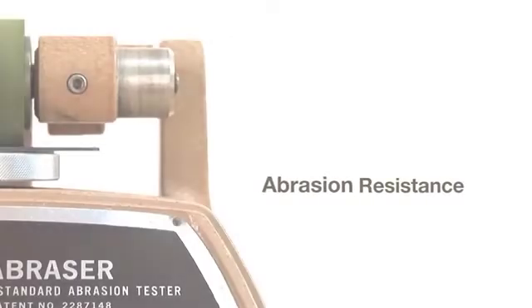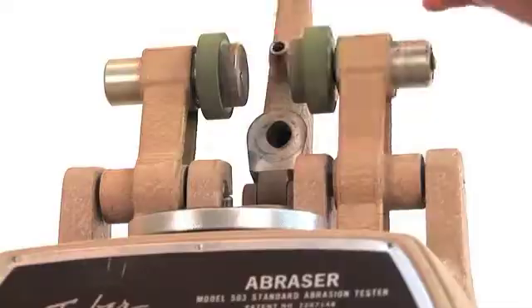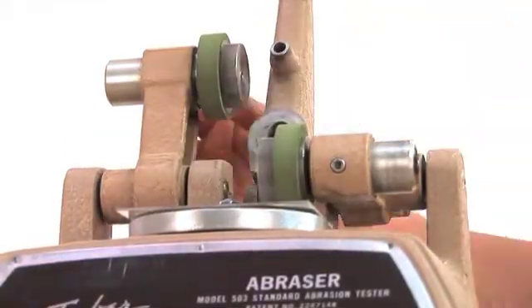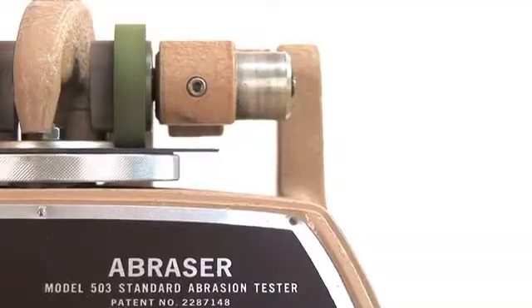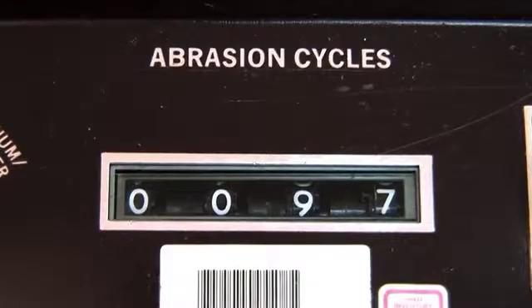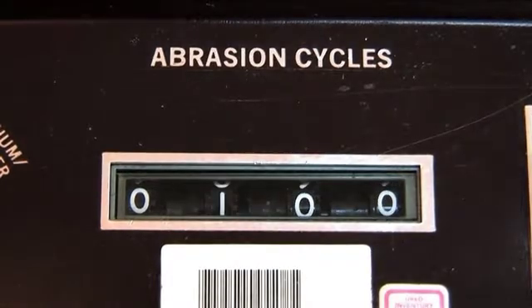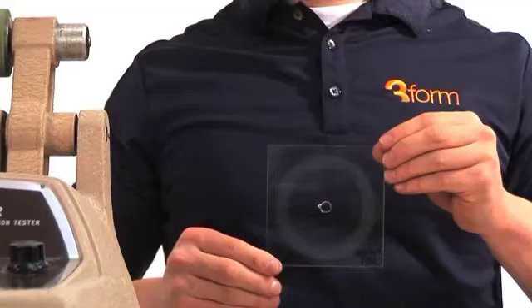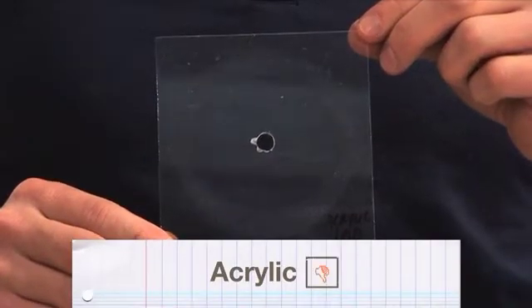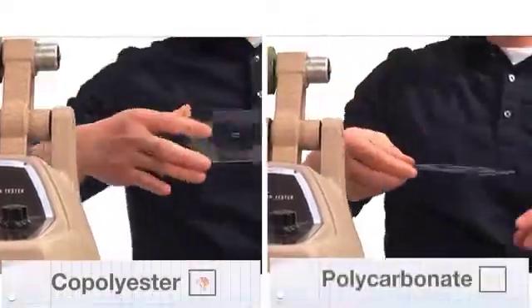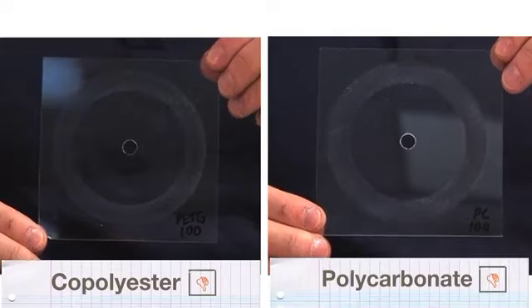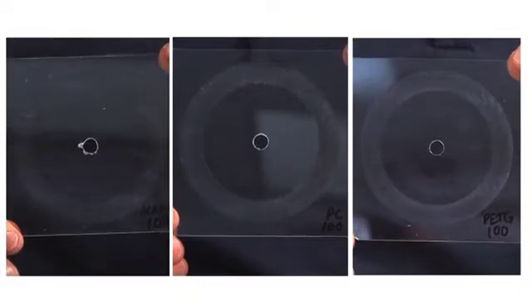Abrasion resistance. How susceptible is the material to scratching? It's an important consideration when you're thinking of things like transaction counters or high use or high traffic areas. In this test, we're showing what happens to the materials after being subjected to 100 cycles in a Taber abraser. In the first test, we show how acrylic performs, and we look at the haze on the surface upon completion of the 100 cycles. After completion of 100 cycles with the copolyester and polycarbonate, you can see the relative difference among materials. Acrylic being the hardest, polycarbonate having a moderate level of hardness, and copolyester being the softest of the materials.